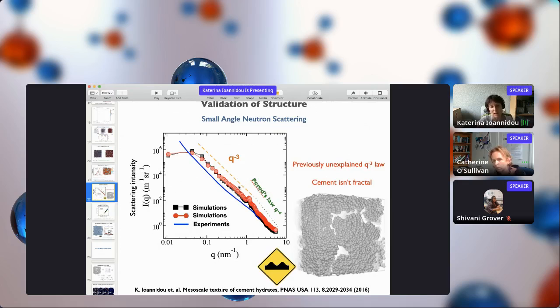So if I don't have this large system, I could never compare with this experimental data. I have the beginning of this curve, but there are systems that can behave very differently. After a while, they can have a plateau, or they can have another peak. To be sure that we have this exponent for 2 orders of magnitude, it was very important to go to a large scale in terms of simulations and particles. So it really depends on the system.